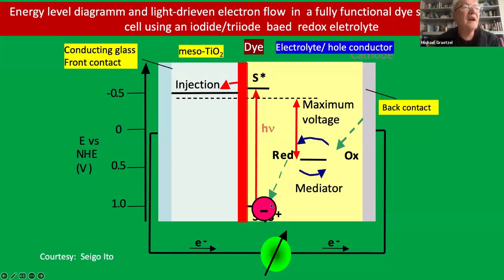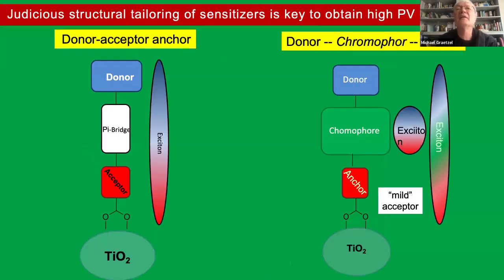So our cells for a long time had trouble getting more than 10% efficiency. 10% was certified, or a little bit over 10%. But today this issue was solved. On the one hand, new sensitizers were developed, and these are organic type sensitizers. And you can see that here, for example, we have a donor-acceptor type molecule. So when you excite this dye, the electron flows from the donor to the acceptor, from the top to the bottom. And the acceptor is linked to the TiO2, which is ultimately receiving the electron. So these are rationally designed molecules that work very well.